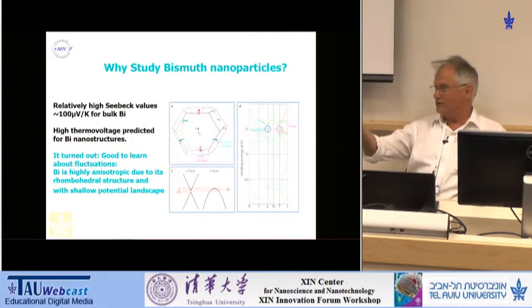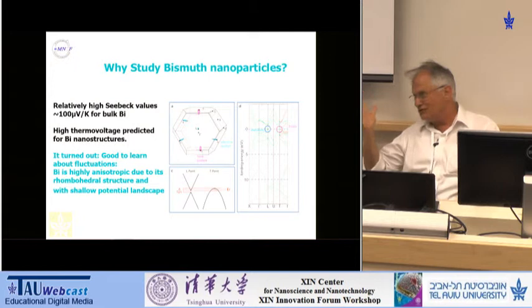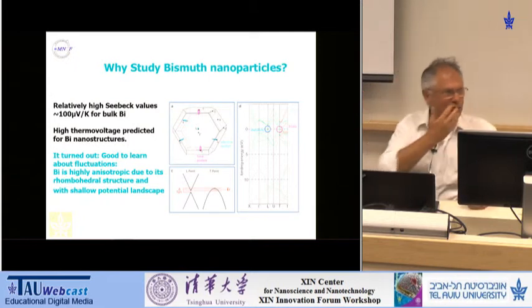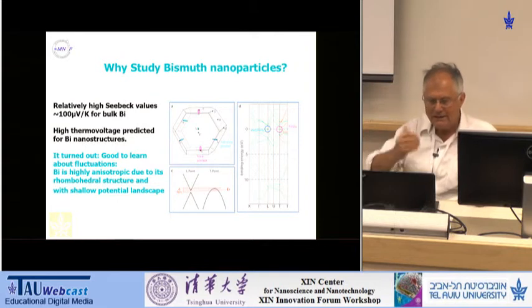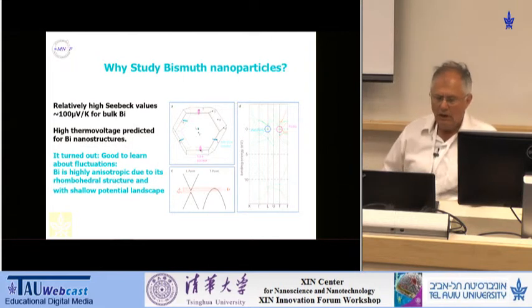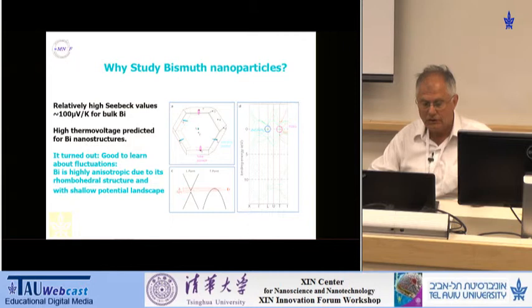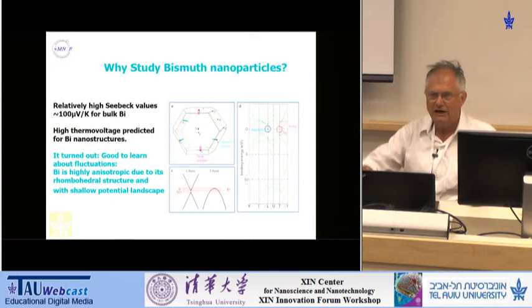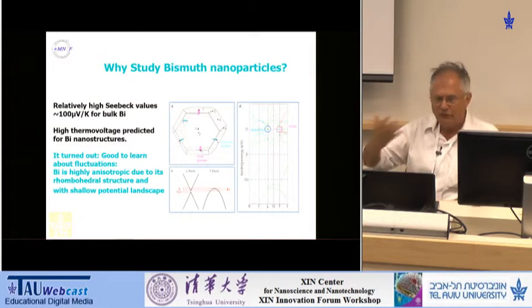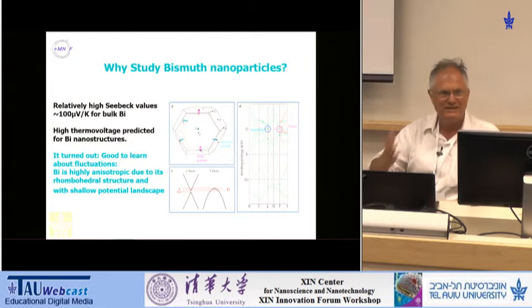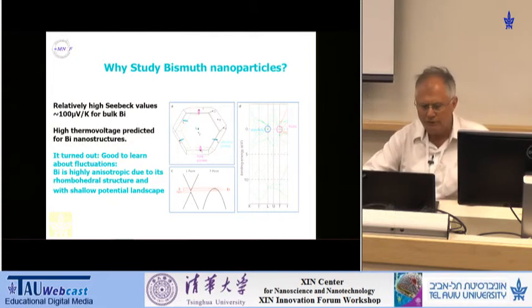And as I told you, theorists, and they're always right, mostly right, predict that the thermovoltage would be extremely high in such conditions, and that's why we tried to measure, I'll tell you in a moment who, the thermovoltage in bismuth nanoparticles. It turned out that they are completely restless. They don't have any uniform properties. It was very disappointing at the beginning, but in fact it turned out to be a very nice laboratory to learn about the fact that nanoparticles do not necessarily have uniform properties.